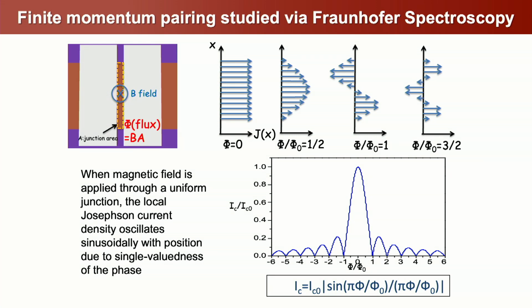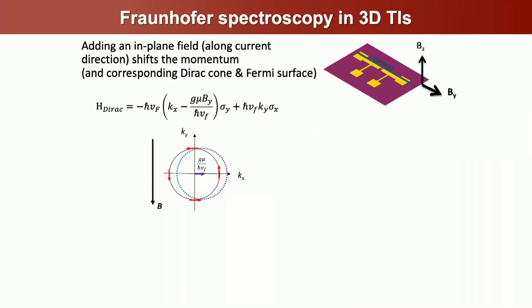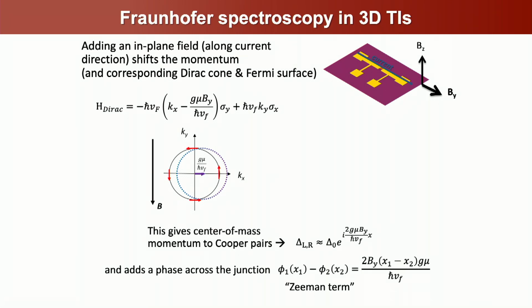Now, the reason this is interesting in topological materials is because of spin momentum locking. When you add an in-plane field, it shifts the momentum, and therefore it shifts the corresponding Dirac cone and Fermi surfaces. And so you should actually get a shift of phase in this case. This additional phase that you get from shifting the Dirac cone gives additional phase to the center of mass momentum of your Cooper pairs. And therefore it adds this phase across the junction, which we call the Zeeman term.